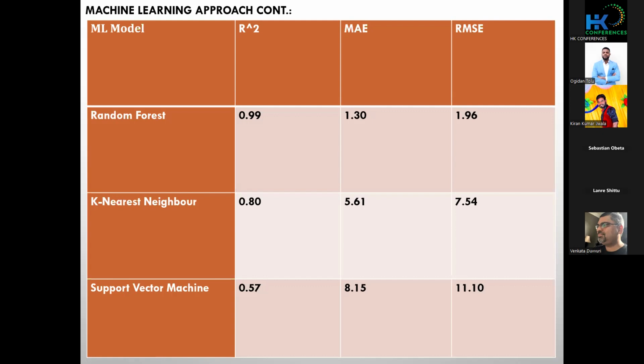So this table was from a research conducted by me. In this research, I utilized random forest regression, support vector machine, and k-nearest neighbor to predict the compressive strength of admixture mixed concrete on a 1030 data set. This table illustrates the performance of the three machine learning models evaluated, employing correlation coefficients, the root mean squared error, and the mean absolute error.